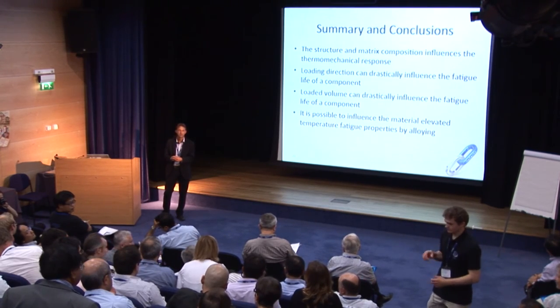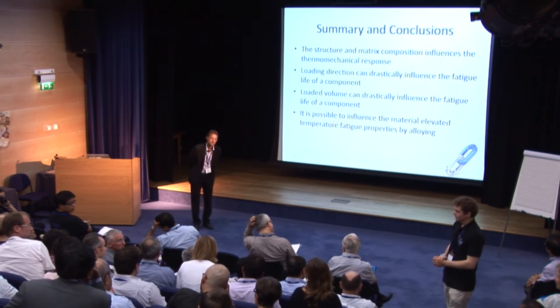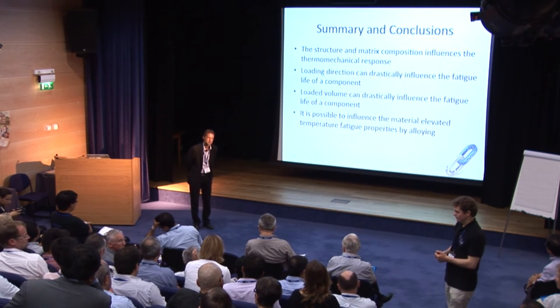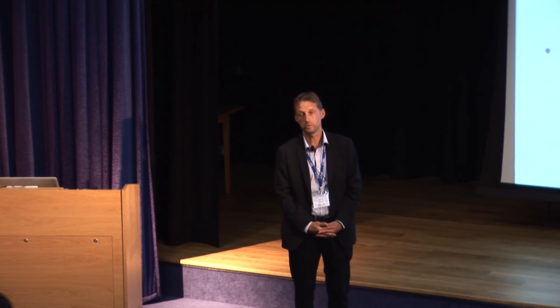I have a question. If I have understood well, you would like to improve the isotropy of the material by reducing the number of elongated inclusions in the steel, so by lowering the sulfur content. But in any case, the oxide content will remain a source for failures during fatigue testing. And what about the machinability of the pieces then? Because sulfur is often considered as improving the machinability. You're absolutely right. What we're doing is reducing the sulfur content, and also the oxide content, and then you will end up with much poorer machinability. But fortunately, we have very good companies working with machining tools, and they are working quite a lot, because today you can find these low sulfur steels and you can machine them, but you need to develop.